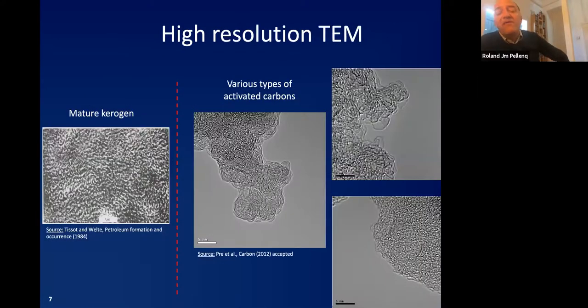But obviously we can go along and try to find an analogy, and this is what people have done. If you compare a mature kerogen on the left to an activated carbon that is produced for the industry, you have a lot of similarities. You can see at the scale of nanometers, because we are at the scale of nanometers when we use TEM, that we have something which is close to a nanoporous carbon that we fabricate every day on Earth for whatever filtering application, for instance, okay? Except that the natural one took, as I said, a long time to cook.